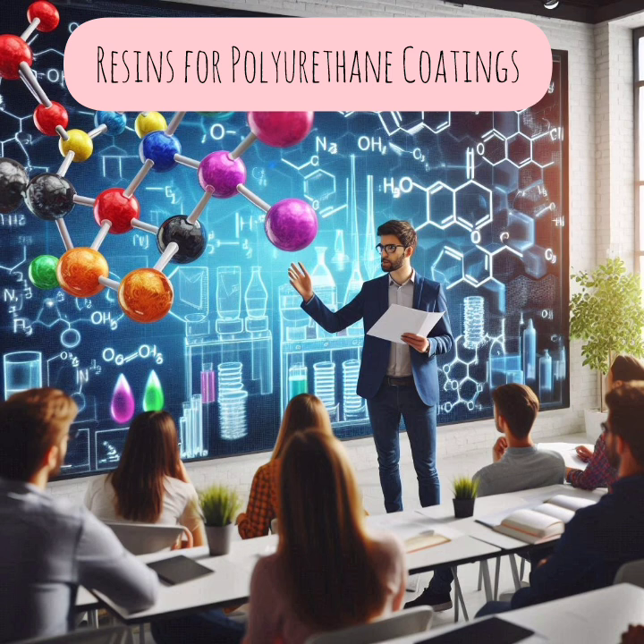Moisture-curing polyurethanes. The principle behind this type of coating is that isocyanate adducts are formed with polyether triols and diols with excess isocyanates, which when applied react with the moisture in the atmosphere to form tough coating films under ambient conditions. They have excellent resistance to abrasion and hence are used as floor coatings. The prepolymer is prepared as follows. A combination of triol and diol polyethers, properly chosen to provide optimum hardness and elongation, are cooked with a diisocyanate at high temperatures in a nitrogen-blanketed kettle and water-free solvents. The prepolymer has excess isocyanate NCO groups, which react with the moisture in the atmosphere to provide hard, tough, abrasion-resistant dry films by solvent evaporation and cross-linking to high polymers.